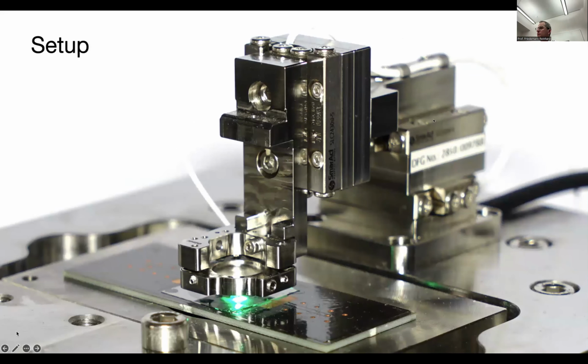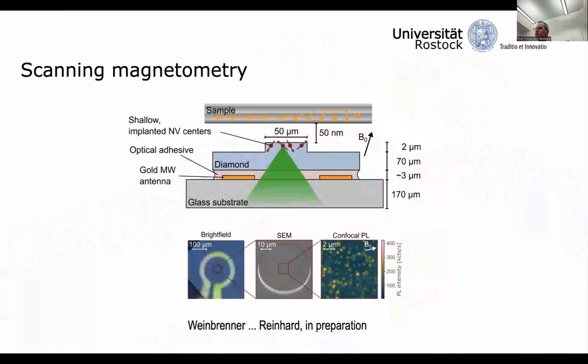So this is the setup that we use. It's roughly 10 centimeters in size. It operates with a commercial standard diamond, and it is a simple upgrade that you can add to essentially any microscope that is being used for NV centers. And we can now do this in an improved generation of devices, which you see here. So we use millimeter-sized diamonds.